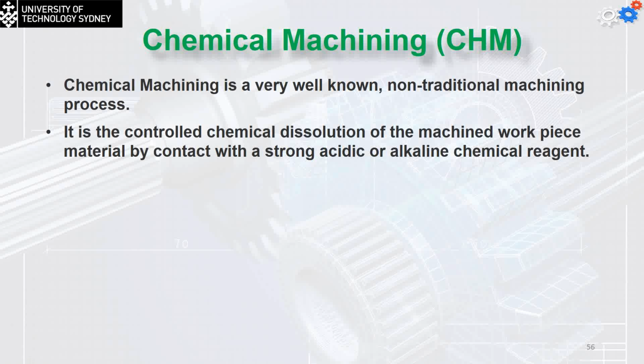So chemical machining is one of the very well-known non-traditional machining processes, and is controlled by the chemical dissolution of the machined workpiece material by contact with strong acidic or alkaline chemical reagents. A special coating called the maskant should be added to protect the areas from which the metal is not going to be removed. This process is used to produce pockets and contours, as well as the removal of material from parts that have a high strength-to-weight ratio.